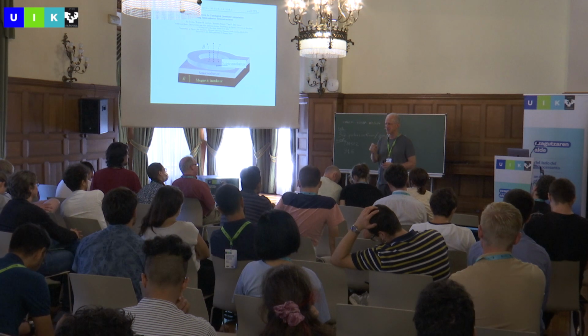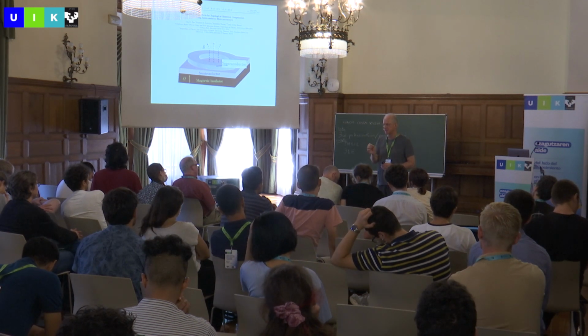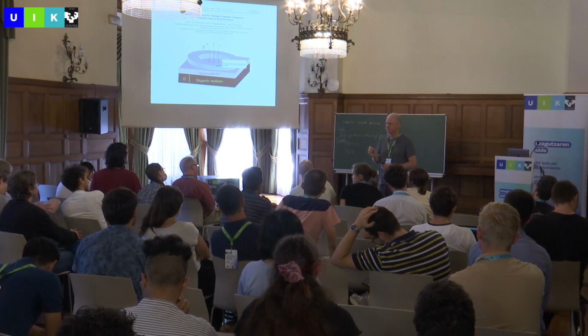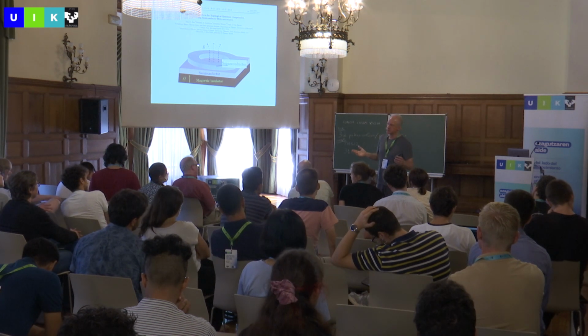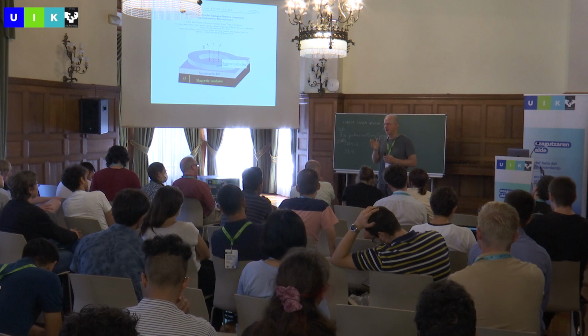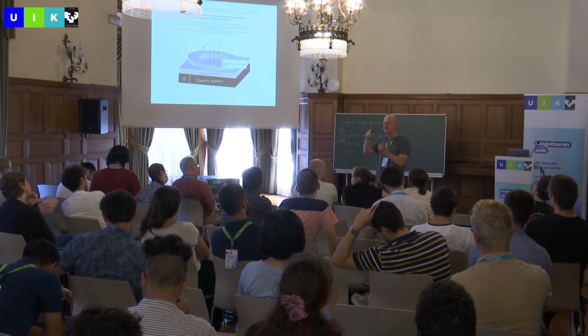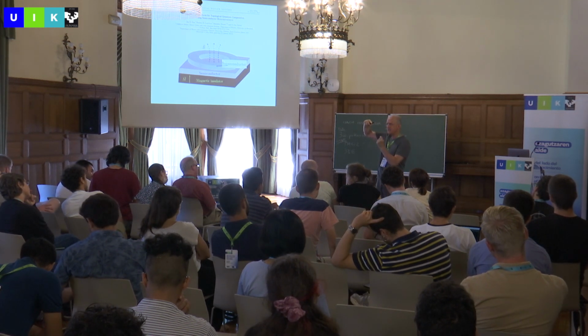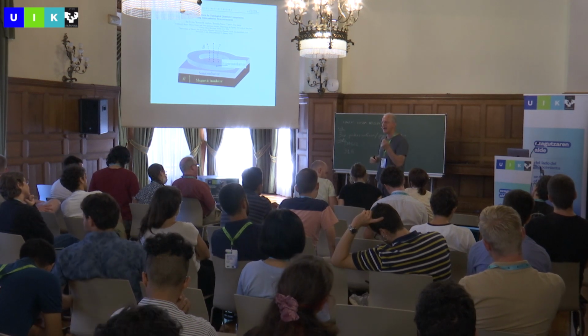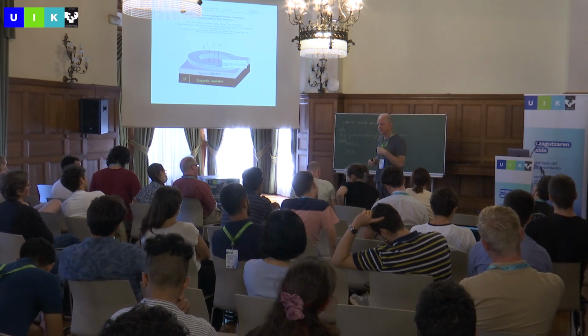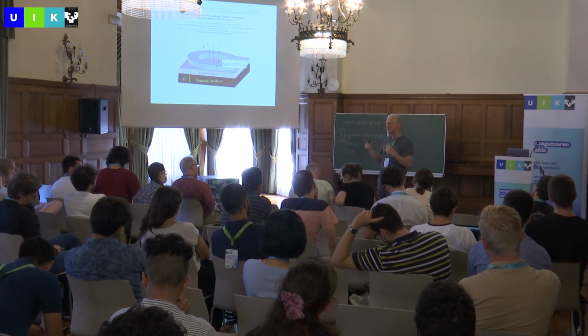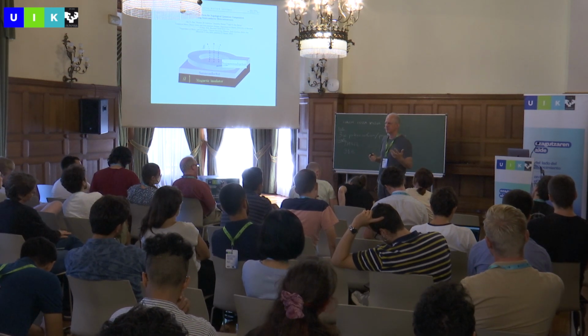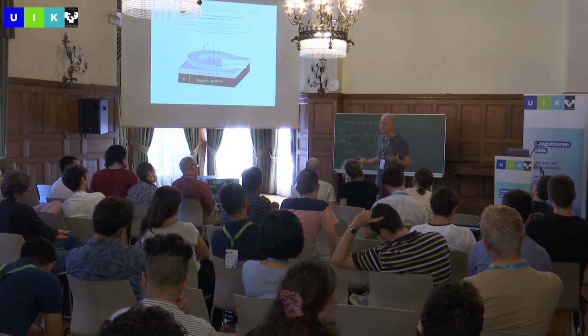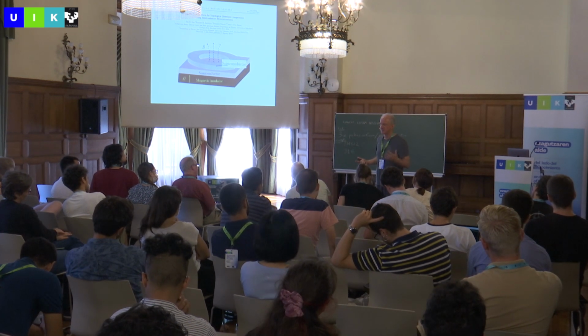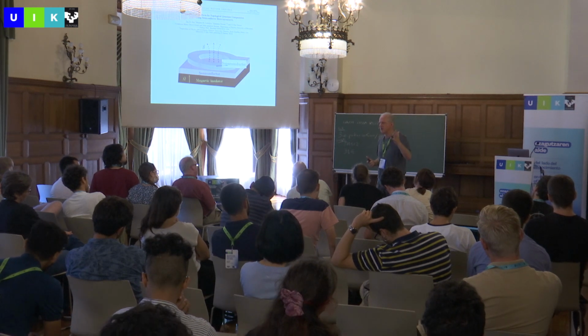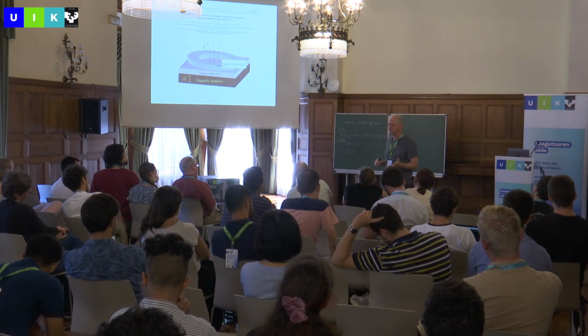And it's unobvious, but it's good that you bring it up because I want to mention it explicitly, which is the G factor. Who cares about the G factor? The reason the G factor matters is because I needed to have a Zeeman splitting in the nanowire that exceeded the gap of the superconductor. Now, if I normally put a Zeeman splitting on a superconductor which is comparable to the gap of that superconductor, I kill superconductivity. That's the Clogston limit. Superconductivity, rather, the singlet, superconductivity is gone.